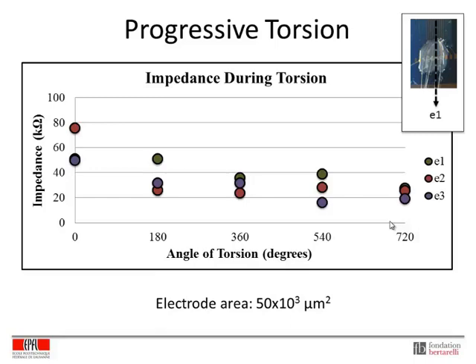The impedance of E1, which is positioned right in the center of the electrode array, is relatively stable over the course of the progressive torsion, while the other two have a wider change in the impedance. This is actually pretty critical due to the positioning of the electrodes compared to the others in the same array. We believe that this change in the impedance is due to the fact that the electrodes on the perimeter are going to be experiencing not just torsion but also stretching.